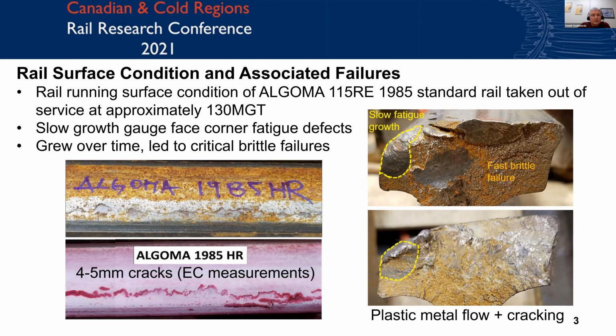To add to that, the rails started developing RCF cracks, especially on the gauge face corner of the high rail. So what you're seeing there is the high rail. That's a picture on the left-hand side top. That's a picture of the rail as we saw it in track, and then the rail when it was treated with a dye penetrant, which is a process where you spray the rail with a dye penetrant. It seeps into the cracks, and then you bring it out with a developer to show the surface crack morphology much better. And that's what we're seeing here. So we measured those cracks, and they were somewhere between 4 and 5 millimeters in the section that had the type of failure that's being shown here on the right-hand side.